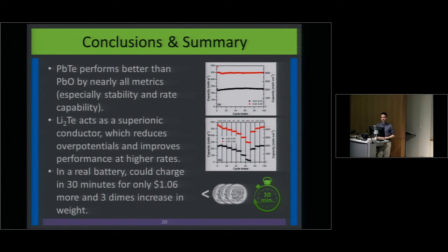So to sum up, the lead telluride performs better than the lead oxide by nearly all the metrics we tested, especially stability and rate capability — you can see over here on the right, just to remind you. We think this is because the lithium telluride acts as a superionic conductor, which reduces the overpotential and makes that reaction easier even at higher rates. And so in a real battery, it would only marginally increase the weight, and you could charge it in 30 minutes.